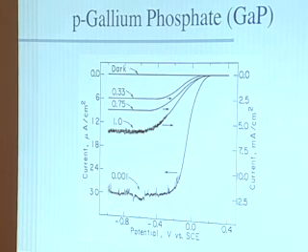What you may not be noticing here, but I'm sure Bruce has, is the currents are much smaller here than in the other scheme. This microamps per square centimeter only refers to this line right here, which is at very low intensity. And the milliamps per square centimeter, these three lines right here. But we're only getting up to about 6, 7 milliamps per square centimeter as opposed to 40 before.